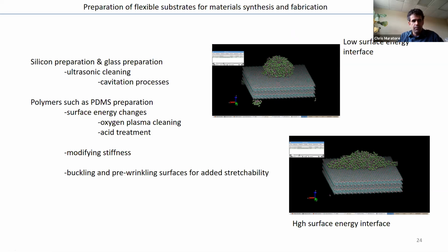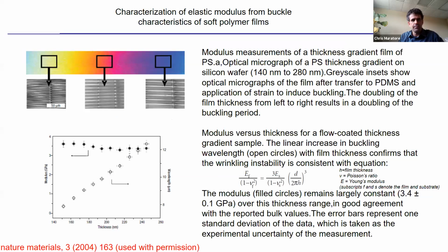And there's different ways to do that. You can use acid or you can use plasma to change that surface energy to get better contact between the metals and the polymers. When you're using polymer-based substrates, there's some nice games that you can play. So when you apply a material to a polymer surface, if that polymer has a very low elastic modulus, so we're talking about silicon having an elastic modulus of 150 gigapascals.